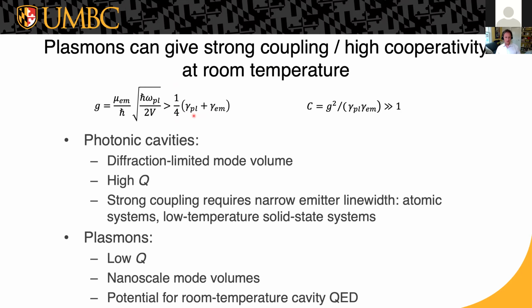You can make very high quality photonic-crystal cavities, for example, that have nearly diffraction limited mode volumes. But the emitter line width is going to be limited by thermal dephasing, especially in a solid state system. So your choices are either to have a completely isolated system, like a single atom or a cold gas of atoms, or to take your solid state system and cool it down to cryogenic temperatures to get the line width to be small enough that you can resolve the two polaritonic peaks.